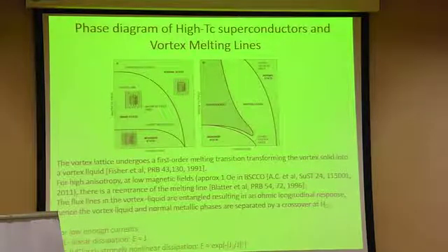And if you plot current voltage characteristics, you will see, probably in my third lecture at this school, a downward curvature in a double logarithmic plot of the current voltage characteristics. And that is the mark of a vortex solid. So vortex solid means the following thing. When you decrease the transport current linearly, the dissipation drops as a power law. So practically you will have very little dissipation if you do not apply a very large current.